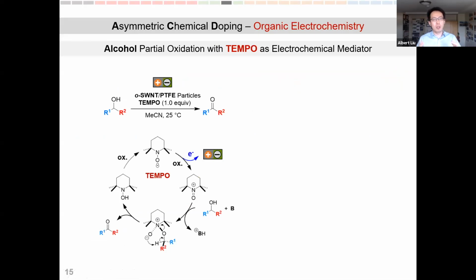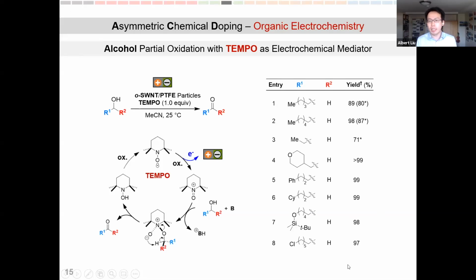Knowing that our particle can drive electrochemical reactions in situ pretty successfully, we challenge our particle and ask whether it is possible to access organic electrochemical transformations inside acetonitrile. The reason being that most biological transmitters and signals are organic molecules, right? So here, as our model reaction for organic electrochemistry, we use partial oxidation of alcohol into ketone or aldehyde, mediated by TEMPO, an electrochemical mediator that couples with our Janus carbon particle, which provides the electricity needed for this turnover to happen. As you can see from this catalytic cycle, we basically chew up alcohol and oxidize it into the aldehyde or ketone that we want. This reaction occurs at basically quantitative yield for a large variety of substrates, showing excellent functional group versatility, which is quintessential for typical electrochemical transformations.